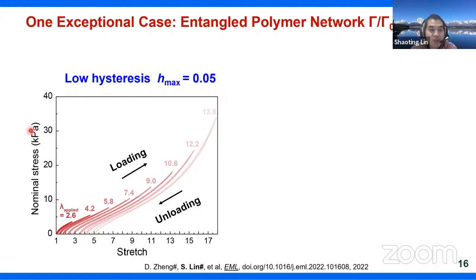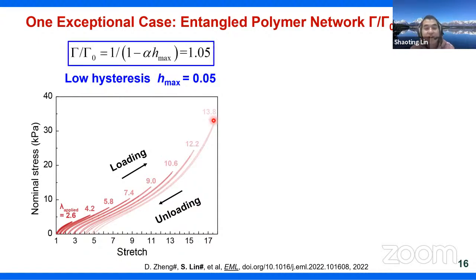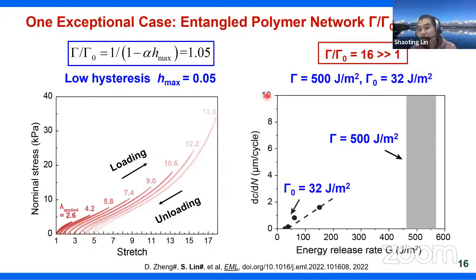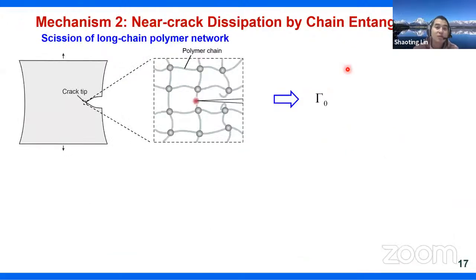This is the nominal stress versus the stretch at different stretch levels. We can see that the hysteresis ratio is really small. Even when the stretch level reaches up to 13.8, the maximum hysteresis ratio is about 0.05. Based on this bulk dissipation model, the toughness enhancement should be no more than 1.05. But our experimental result found that the ratio between gamma and gamma 0 is a 16 times difference. That means there must be some new physics behind this entangled polymer network. We really want to understand what's behind this intrinsic material system.